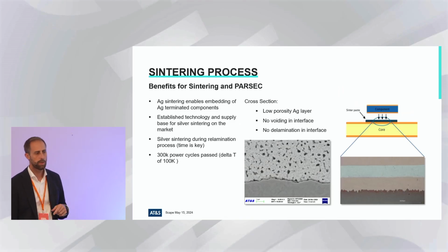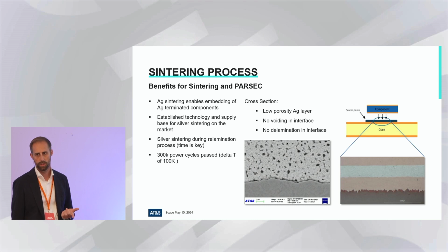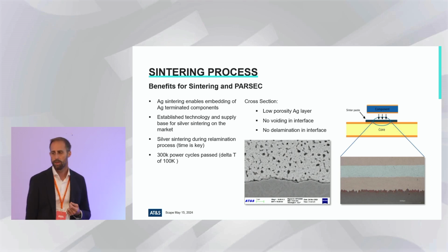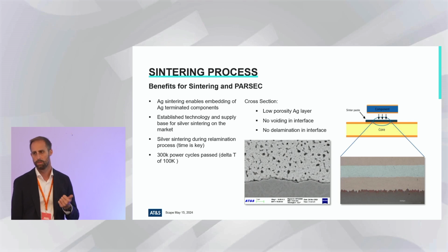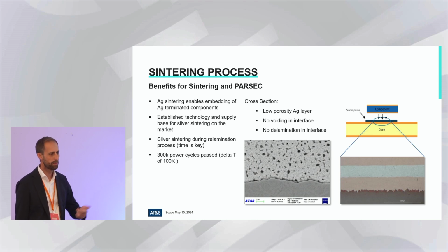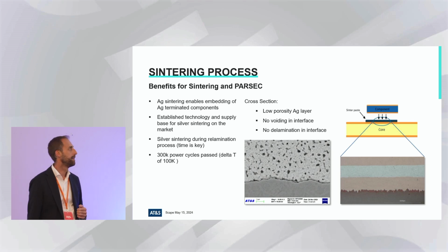with the PARSEC approach in the center. So the center core, the PARSEC core, will always stay the same, and then you do the interconnection via sintering. Also important, we will do the sintering process during our lamination process. So what's the benefit of this? It's two elements. Low pressure on the die, and we have a lot of time. We will anyway laminate 2 to 3 hours in our prepreg configurations here. So we can give the silver all the time that it needs. And that is a big benefit.